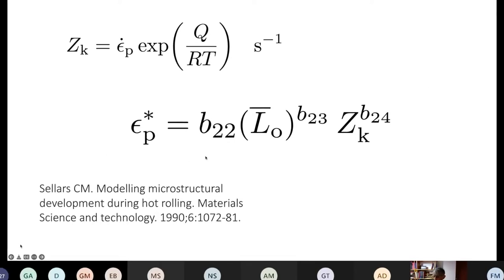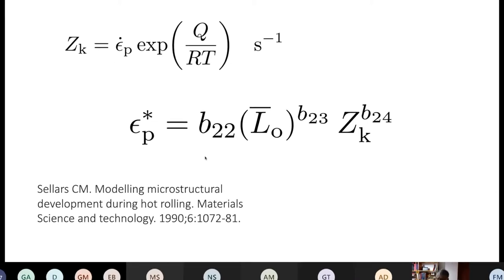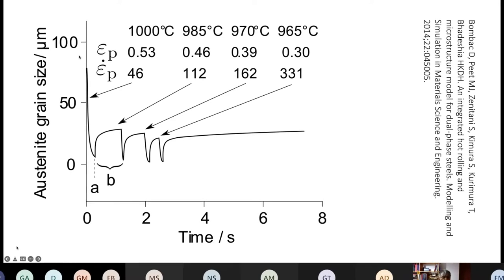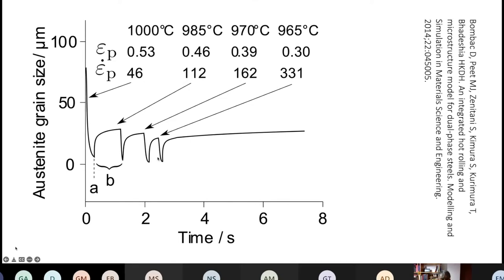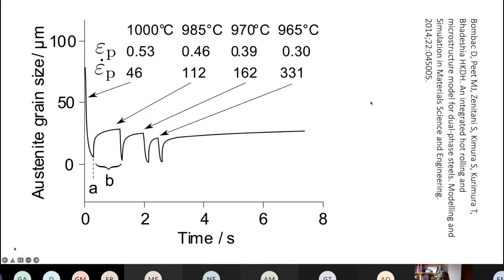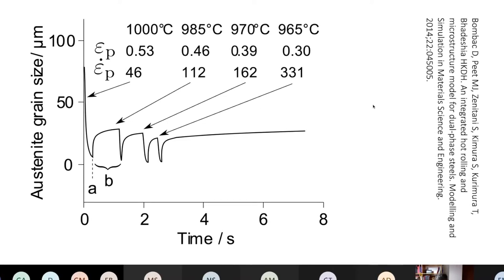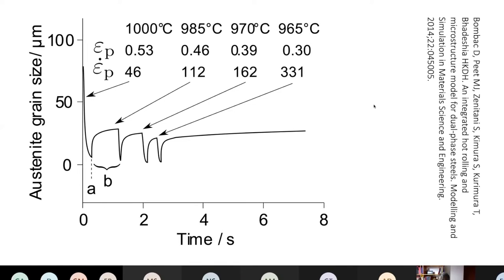These equations for many different kinds of steels are available from a large amount of experimental data. Control rolling is not just a single hot rolling pass — there are multiple passes between multiple rolling mills, with grain refinement and recrystallization cycling, until you reach a finished rolling temperature, which is important in determining your ferrite grain size.